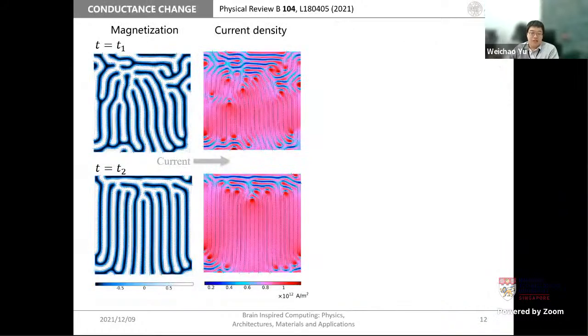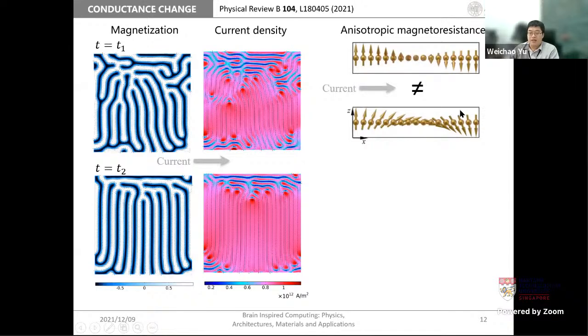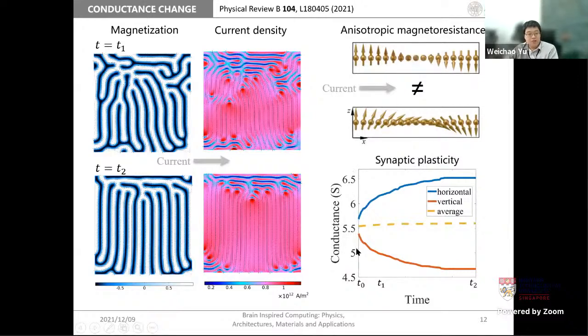As we have mentioned, in the presence of AMR, the conductance state depends on the magnetic configuration. For example, the conductance of a Bloch wall and a Néel wall will be different. So we can calculate the conductance of this film at each time step according to that simulation. The blue curve here is the horizontal conductance, which is calculated according to the left and the right edge. It increases with time and finally reaches saturation. The red curve stands for the vertical conductance, which is calculated from the top and bottom edge, which decreases in an almost symmetrical way. This feature indicates that the magnetic textures have so-called plasticity and can be used as artificial synapses.